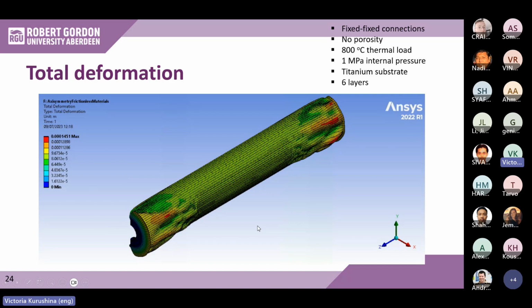These results show the total deformation. You can see that the maximum deformation is within 140 micrometers. But again, this is a really worst case scenario for these specific materials. At the same time, the wall thickness, I will reiterate, is about 2.5 millimeters.